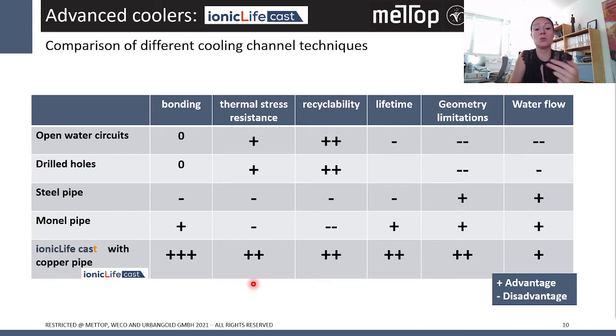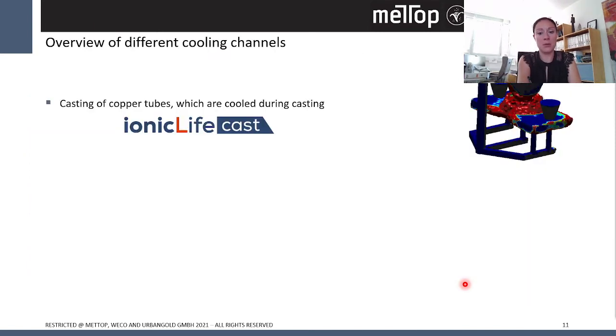Because of the two identical materials, you have a perfect thermal stress resistance. You can also quite easily recycle those coolers. So it's just pure copper. You can just remelt it. Also the lifetime is very, very nice. And you're also not really limited with geometries, since the copper pipes are very, very easy to bend, very easy to produce. You can think of very, very difficult geometries. And also, since it's water just in the pipes, you don't have any cold spots or hot spots like you have in open water circuits. So this is very unique about these coolers.